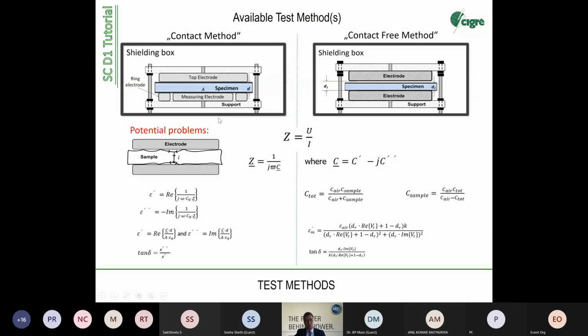The contact method is easy. You take two plates, put the sample in between, measure the thickness of the sample, and you normally work with the guarding arrangement on the ground electrode. So you have a measuring electrode in the middle, because you don't want to measure the surface, or you don't want to have an influence of the surface currents. You just want to have the bulk currents through the material. And your analyzing equipment is connected to the top and bottom electrode. Both methods determine the impedance Z, a complex impedance. It's the complex voltage phasor divided by the complex current phasor. Then from here, you calculate the complex capacity. From the complex capacity, you can derive permittivity and the tangent delta.